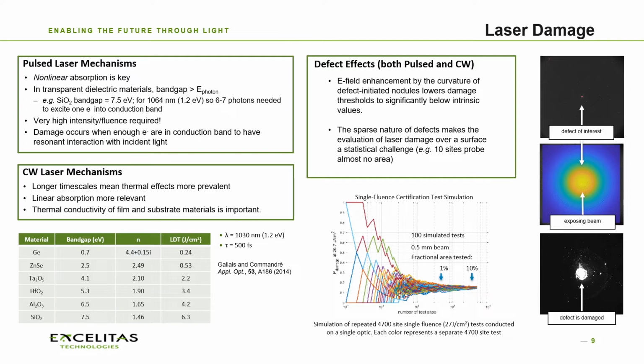For CW damage mechanisms, really it's the linear absorption that's key. Here we're looking at thermal effects usually. Sometimes the thermal runaway types of effects are really critical. So we're going to focus in on the linear absorption, and then finally for both categories of laser system, the defects are typically going to dominate. So most of the damage is actually going to occur at defect sites.